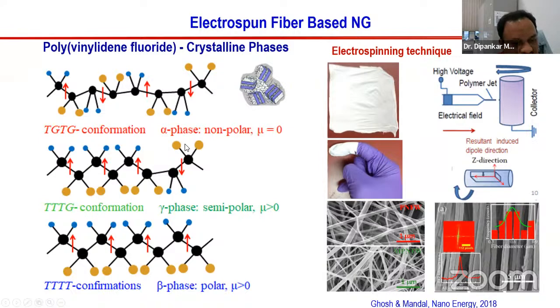But there is another phase, an intermediate phase, called the gamma phase. These three are trans. This gauche is like a defect, in the opposite direction, so this will get cancelled. However, here you will get some sort of polarization. So this is semi-polar, but it also shows piezoelectricity. But in order to get the best piezoelectricity, one has to induce the beta phase.